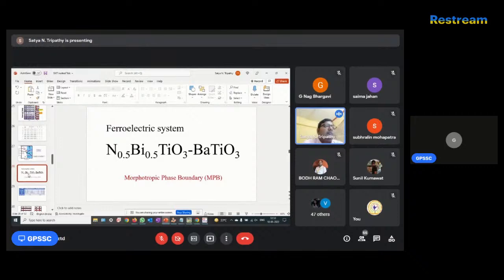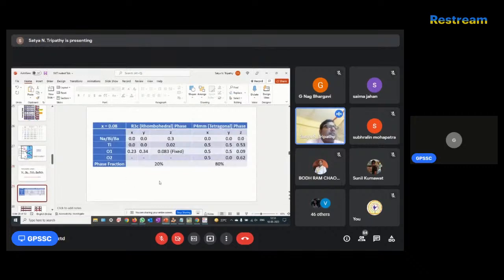So with sodium bismuth titanate, we are using barium titanate. If you do that, different structures will coexist. Sodium bismuth titanate has R3C, and barium titanate is tetragonal. So we can see a tetragonal and rhombohedral coexistence. Here I have shown one of the atomic positions for the refinement. This is for the A site of ABO3, barium sodium bismuth titanate, and this is for the P4mm tetragonal phase.